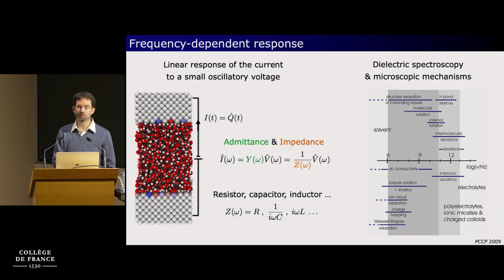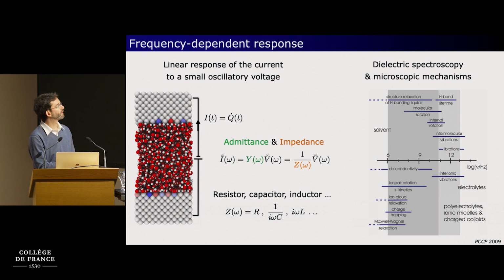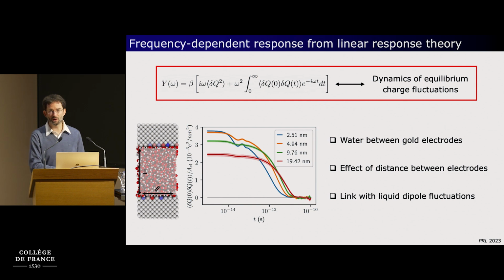And it's very related to what people measure in spectroscopy. The spectroscopy could be at very high frequency, what Misha told us about, but at a lower frequency, it's called dielectric spectroscopy, especially if you want to probe the effect of ions and the conductivity of ions, and the solvent dynamics around ions, and how ions move with respect to each other, and so on. So the goal is to make predictions for the impedance and admittance, and correlate that with the microscopic mechanisms that are also measured experimentally, or at least to be able to interpret experiments based on the molecular information we extract from these molecular simulations. And so we derived a linear response expression for the frequency-dependent admittance.